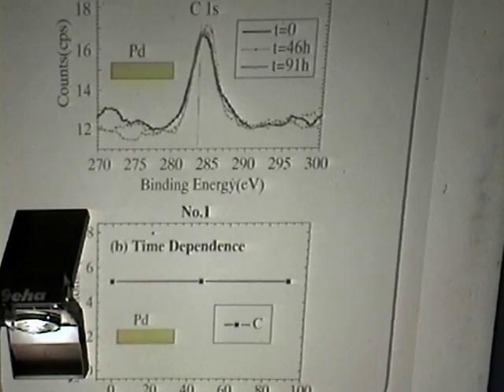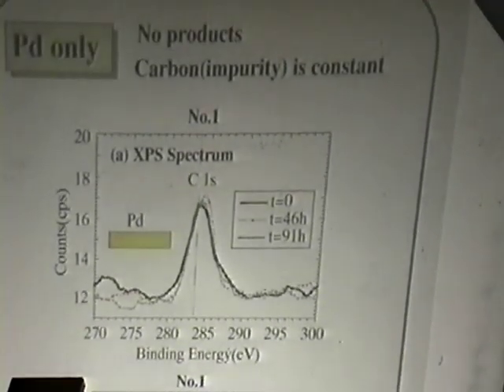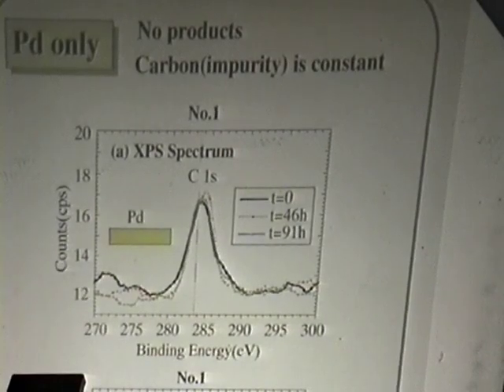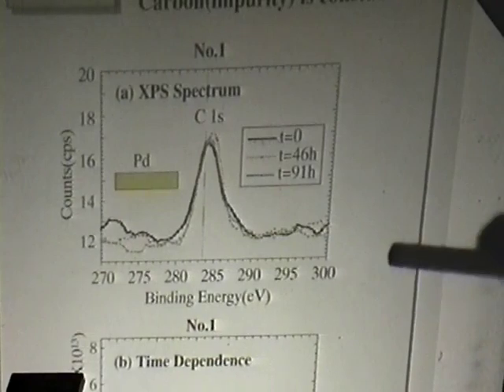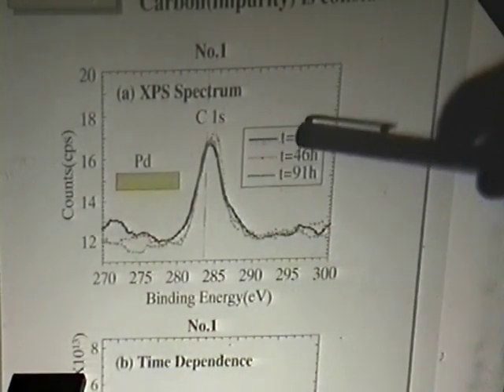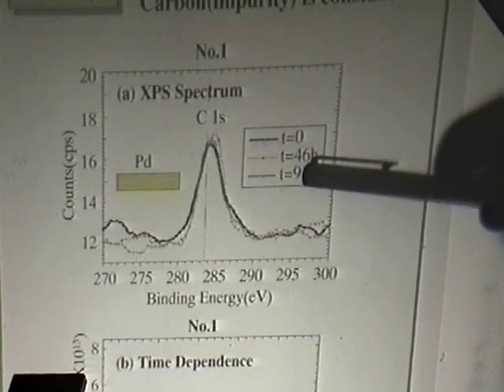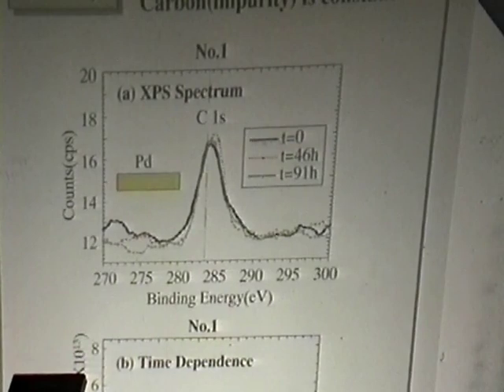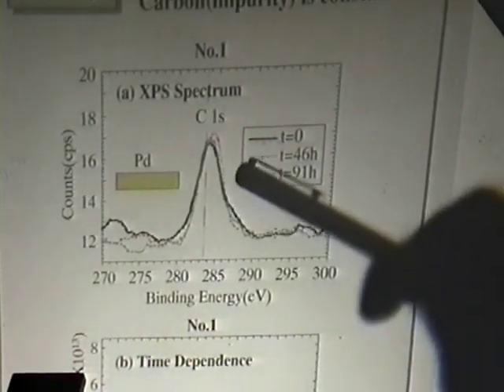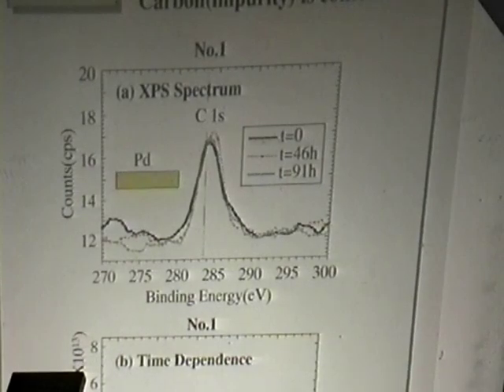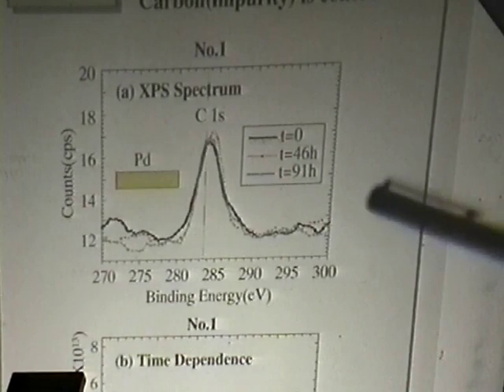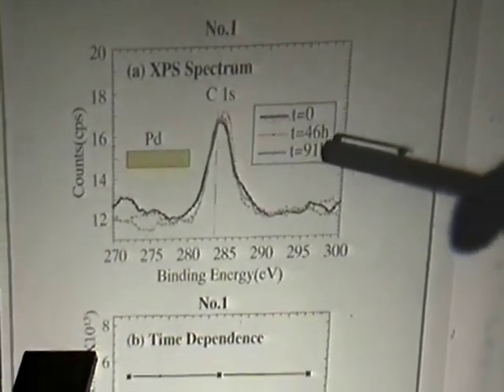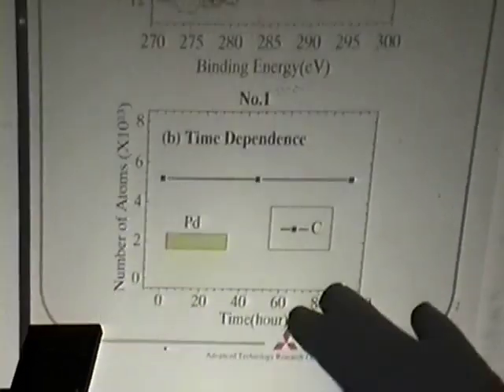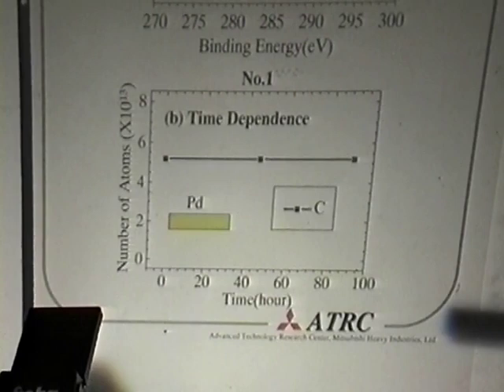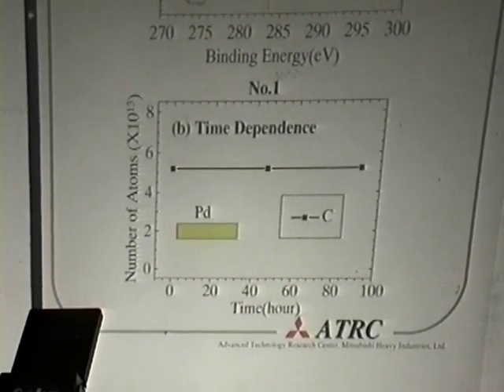The first sample is palladium only, which does not belong to the multilayer palladium. The upper figure shows XPS spectra at T equals 0, T equals 46 hours, and T equals 91 hours. These peaks are attributed to the C 1s photoelectron. We can see that there is almost no difference between T equals 0, 46, and 91. The lower figure shows the time dependence of the impurity carbon. Carbon is constant, as you can see.